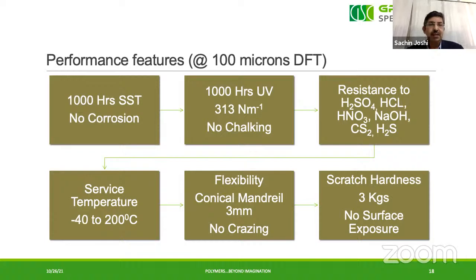So 1000 hours salt spray facility, absolutely no corrosion, tested at all NABL accredited labs, even international laboratories in Dubai and UK. 1000 hours of UV at 313 nanometer lamp, no chalking, no color fade, no change in properties, very high resistance to chemicals like sulfuric acid, hydrochloric acid, nitric acid. Now 33% nitric acid, if you dip the normal plate in 33% nitric acid, in 8 hours it gets dissolved. And this has an excellent resistance to nitric acid, boiling caustic, all gases, CS2, H2S, absolutely very tough, very high